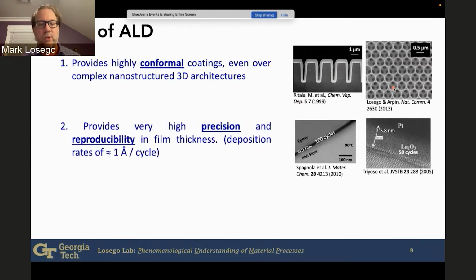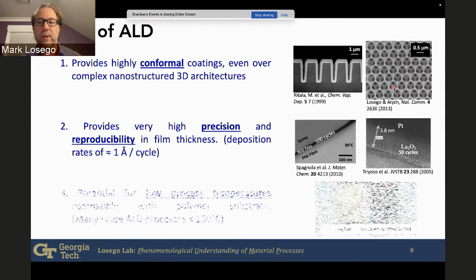Similarly, what you saw there with that animation was that we're putting down one atomic layer at a time. So we have very high precision in terms of the thickness. We can deposit one atomic layer, we can deposit 25 atomic layers, 27. We can be very precise in how much material we're depositing on the surface using an ALD process.